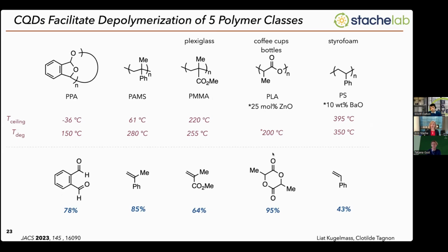methacrylate monomer. And then, very excitingly, an increasingly used biorenewable polymer, polylactic acid, depolymerizes with very high efficiency back to L-lactide monomer in 95% yield. Now, this is very important, for one, because we're getting L-lactide monomer and not seeing any racemization of those stereocenters. So you need the L-lactide in order to get the properties of the PLA. And also, polylactic acid is best recycled through chemical recycling to monomer. It actually doesn't break down in the environment very quickly. It can be recycled under certain conditions in a recycling center, but chemical recycling to monomer is really the most efficient pathway for this polymer.